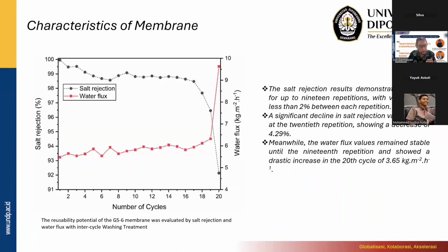Okay, we also do the cycle test, because the problem of this membrane is salting out, like deposits of salt. So we have to clean the membrane, and after that put it in the module again, and so on. So we ran the membrane until 18 cycles. Actually it was 20, but after the 20th the salt rejection decreased so much, and the flux increased suddenly. So we can say that we can use this membrane for 18 cycles, much lower compared to the GO, right? And the silica alone.